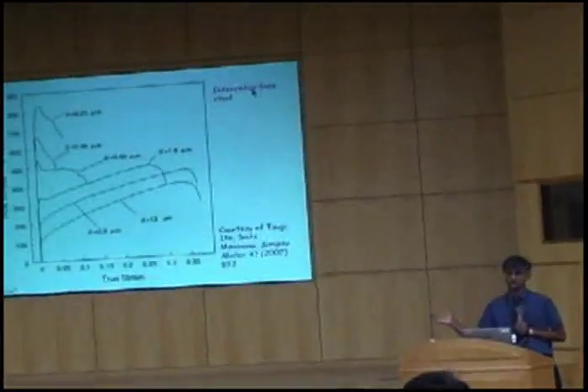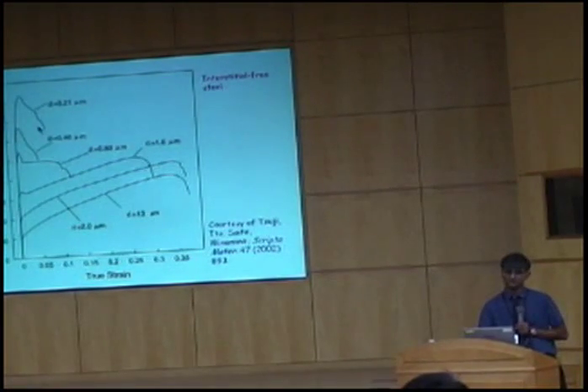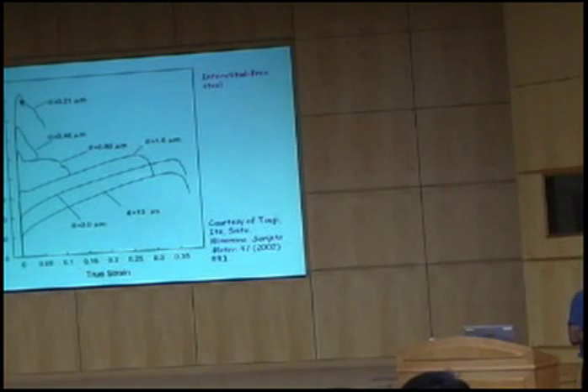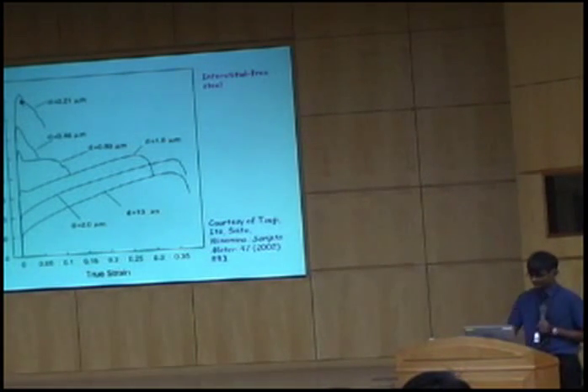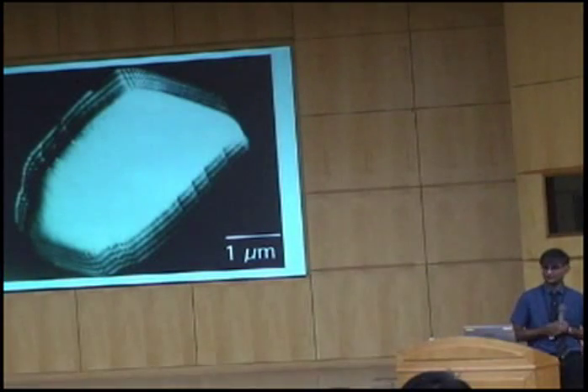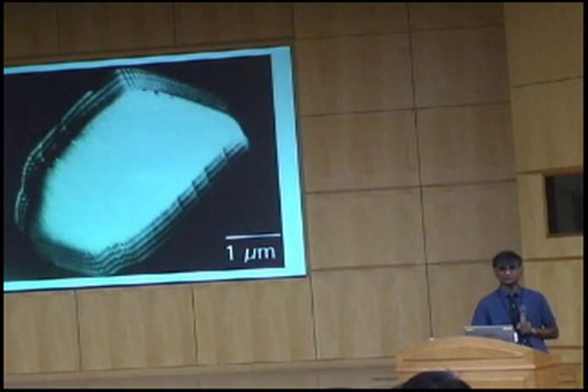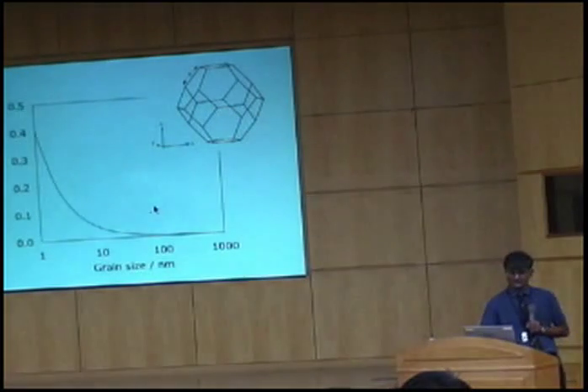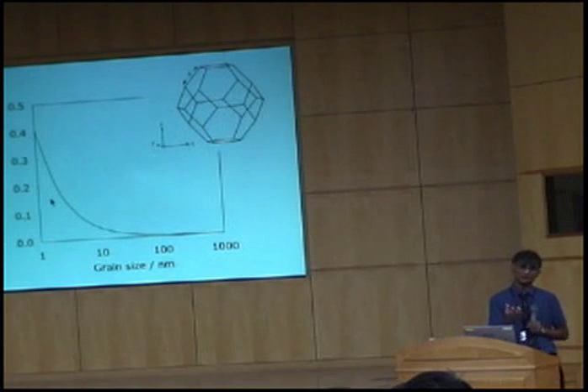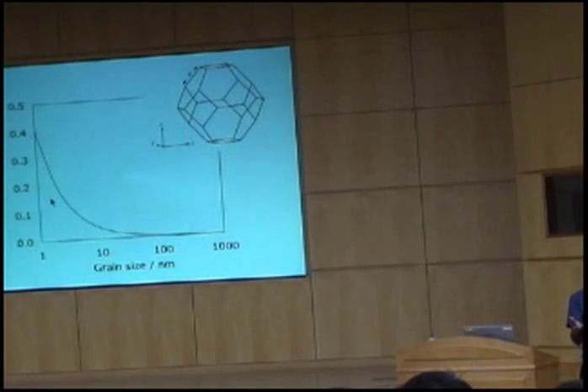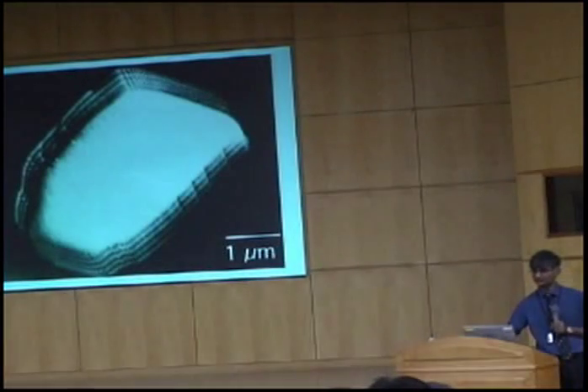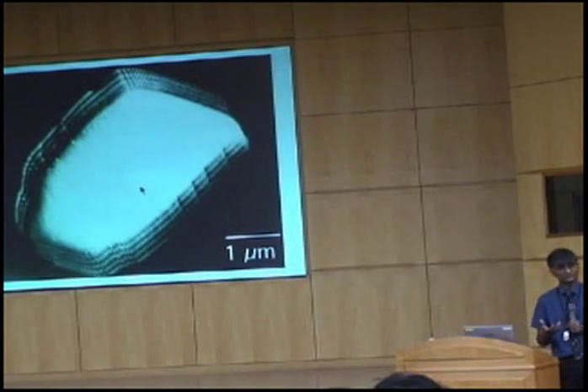And so this is a case for aluminium here. You can see aluminium, and similar results for steel. As you go to finer and finer grain sizes, you basically have zero uniform ductility. And that's, of course, no good in engineering applications. The reason is, of course, that when I reduce the grain size, the dislocations end up in the boundaries and there's nothing left inside the grains. Yeah, simple reason, as I reduce the grain size, the amount of volume occupied by the boundaries increases. Yeah, and the boundaries are very good sinks for dislocations or for vacancies, etc. So the grain becomes clean from dislocations. You can see that here. There's nothing inside the grain. So you can't have work hardening. Okay.